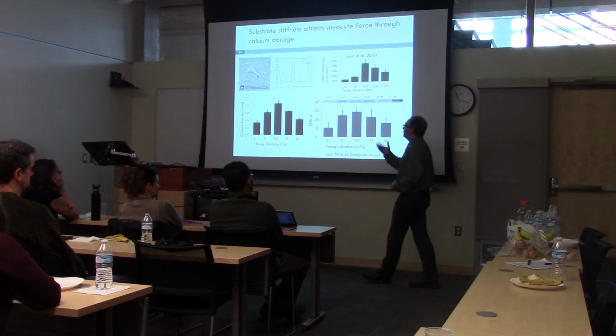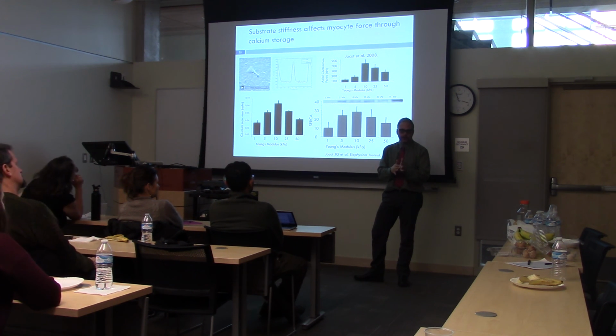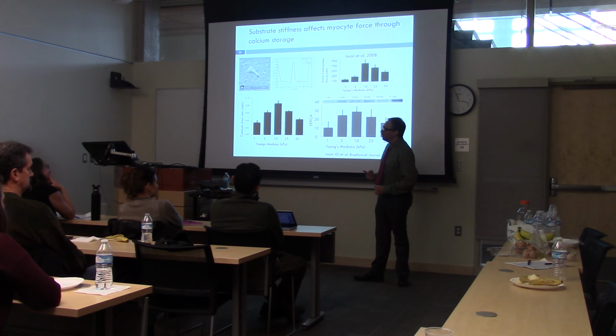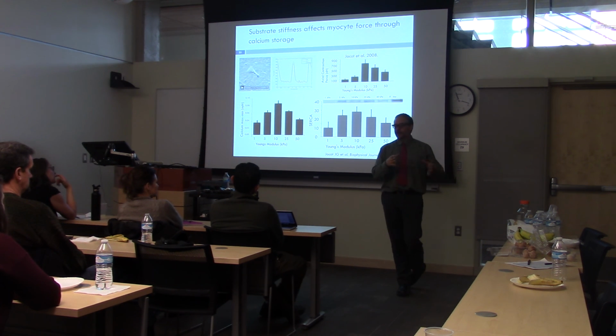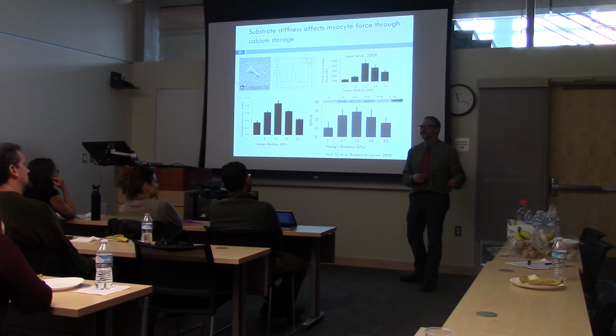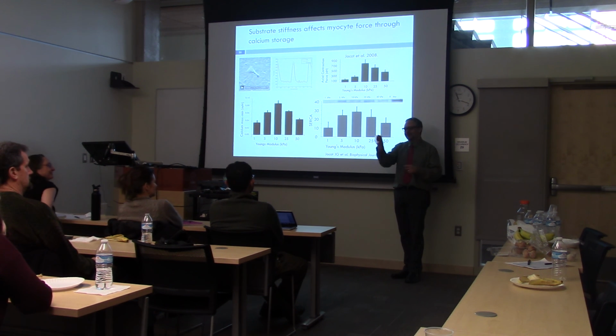I can measure this; it really comes from measuring the exact shear modulus of the gel. So you know how much shear is required to move these hydrogels. And the mathematics aren't that complex. I actually managed to get from a library this book published in 1880 or something, which had calculated all of the mathematics. Boussinesq is the author. It calculated all of the mathematics for point forces moving on an infinite elastic half space. You know, the shear modulus of the infinite elastic half space. How much shear